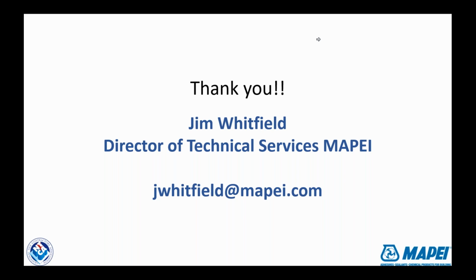But GPT, as Jim said, the minimum joint for gauge porcelain tile, period, is 1/16 of an inch. Now, most manufacturers recommend much wider than that in an exterior. Interior, I'm sure you can get away with 1/16 of an inch, but exterior, consult the manufacturer. Before I came to work at MAPEI, I was working for a tile manufacturer, and the recommendation was 5/8 of an inch in the case of an exterior. They're very specific about that, and I believe some of the others have similar recommendations.